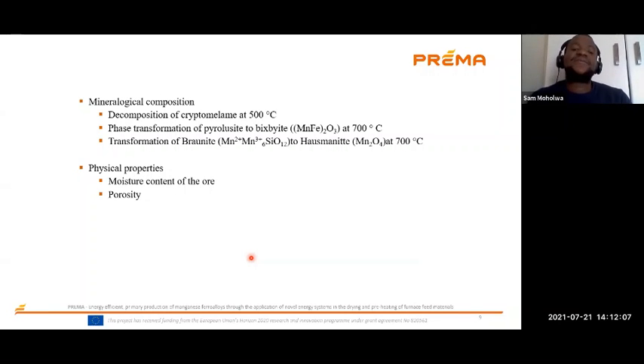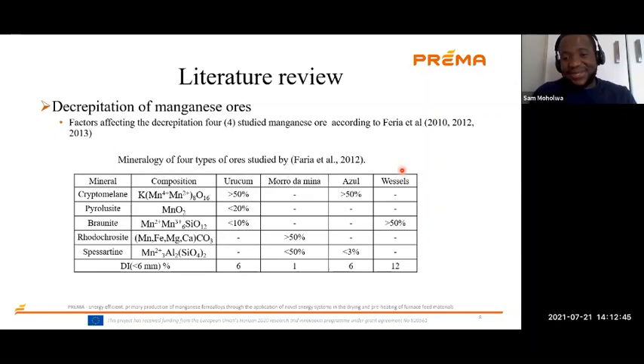Then the other thing is the phase transformation of pyrolusite to bixbyite at 700 degrees Celsius. Transformation mainly means that a certain mineral is transforming into another mineral. And this transformation leads to volumetric changes that induce cracks that lead to decrepitation. And we also have a transformation of braunite to hausmannite. If you can go back to the mineralogy here, we can see that the Wessel's ore is mainly composed of braunite. The transformation of braunite is the one that contributed to the highest decrepitation index of the Wessel's ore. That's why you see that this ore has the highest decrepitation index.